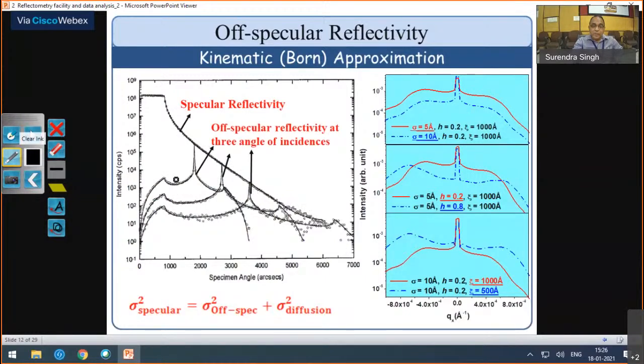And if you calculate the complete picture, you can see how this off-specular reflectivity changes by changing these parameters, other parameters we got from specular reflectivity like density, layer thickness, roughness. Roughness is again a combined thing in the specular reflectivity, but if we preserve those...